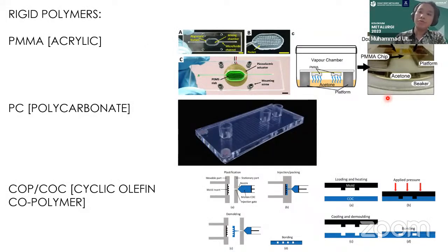So another material that we can use to get micro products is rigid polymers. So we can basically use just PMMA or acrylics, something like this, using maybe laser engraving or micromilling. We can get this kind of small channels, and then we can flow liquids into these channels, and we can try to bond acrylic chips using this kind of method. So basically using acetone gas, we expose the acrylic to acetone gas, and then we can bond them together.